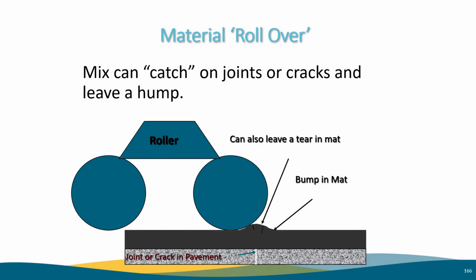Here's what basically happens. It is called material rollover. When going over existing joints, the mix will tend to catch on the joints or cracks and leave a bump. Once this occurs, it will worsen with each pass. This bump can also leave a tear in the mat.